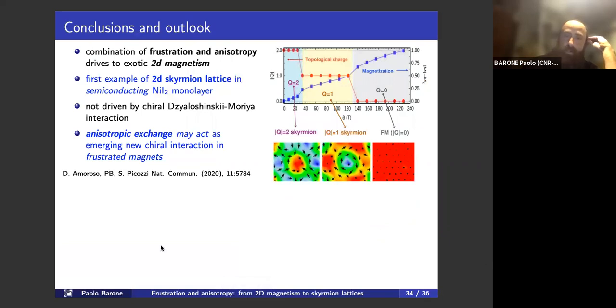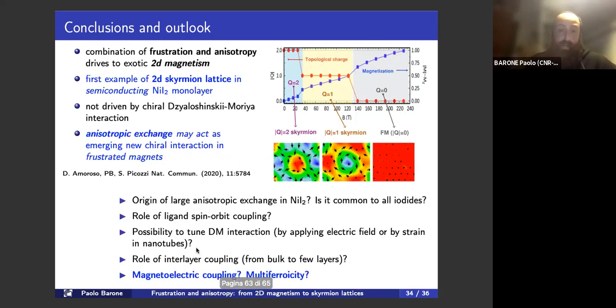Okay, so I think I can conclude. What is really crucial is the combination of frustration and anisotropy that may drive an exotic form of two-dimensional magnetism. What is interesting in this case is that we are considering a system which has no Dzyaloshinskii-Moriya interaction, and it is the frustration of an anisotropic exchange that may act, even though locally it's not a chiral interaction, when placed on a geometrically frustrated lattice in combination with strong magnetic frustration, it can form a chiral magnetic configuration. There are a lot of open questions and issues.